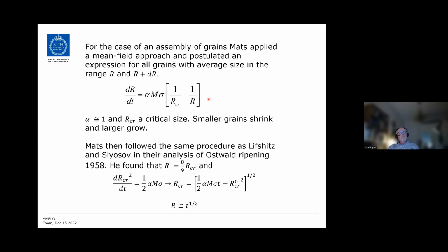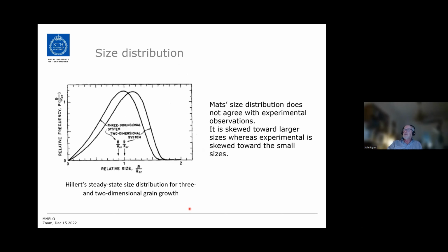And then, of course, you need to see how this could be transformed into an equation for the average grain size. How does that develop in time? Then he used the same procedure as Lifshitz and Slyozov used a couple of years earlier when they analyzed Ostwald ripening. He found that the average size was proportional to the critical size, and he found a differential equation which was easy to integrate, so you could calculate how the critical size depends on time. And so approximately this gives a critical average size which is proportional to the time raised to 0.5. And that is in agreement with the experiments.